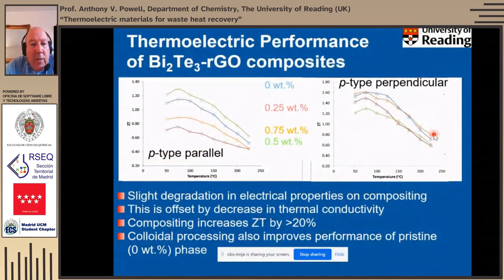And what that does is it increases our figure of merit. Although we get a slight degradation of the electrical properties when we make the composite, that's offset by those quite substantial decreases in thermal conductivity. And we end up increasing ZT by about 20%. At our maximum ZT here, in the perpendicular orientation, we can get up to about 1.6, for instance. What's also interesting, though, is that we can actually improve the performance even of the pristine phase that doesn't include the carbon. And we think that's because by putting it through this colloidal process and the ultrasound, we reduce the grain size quite significantly, and that can contribute to reduced thermal conductivity and consequently higher thermoelectric performance.